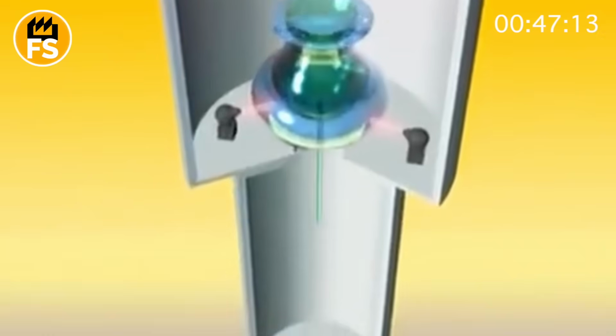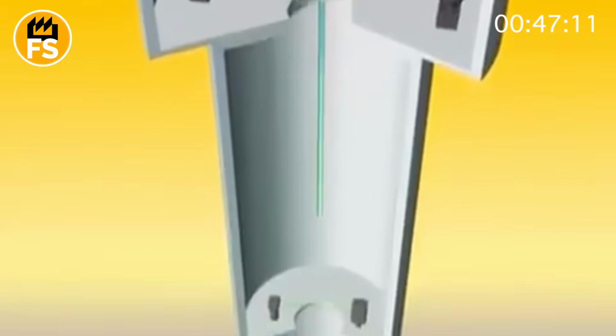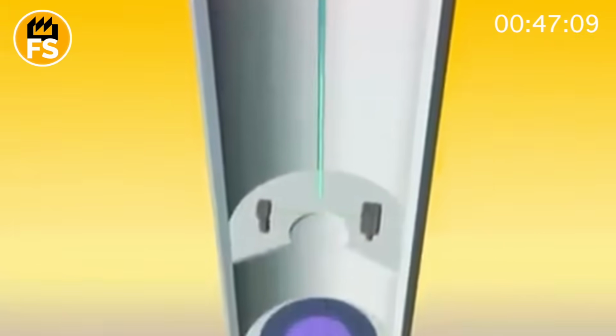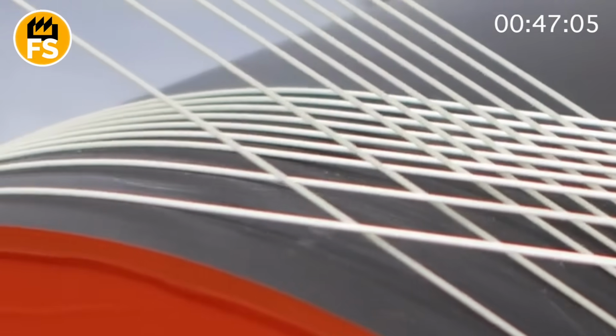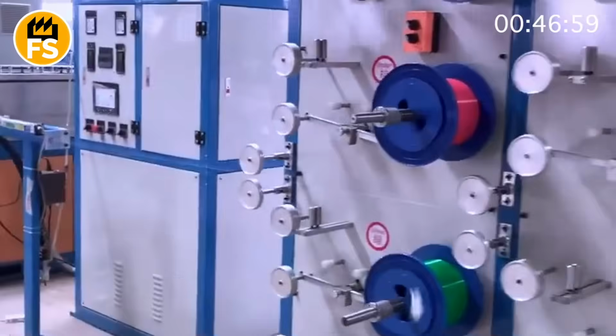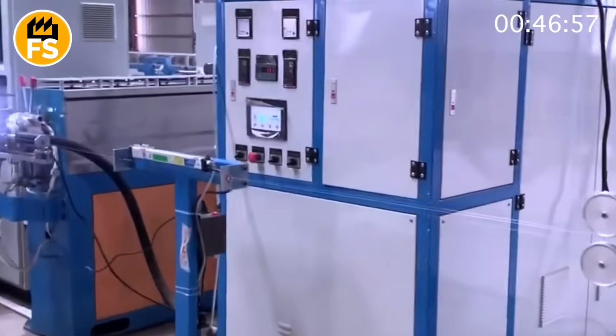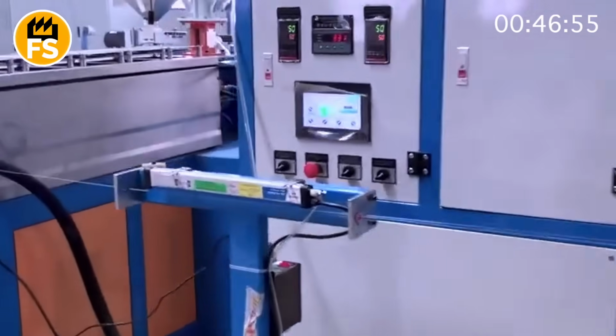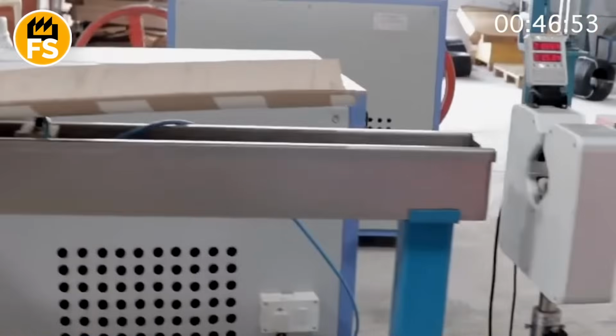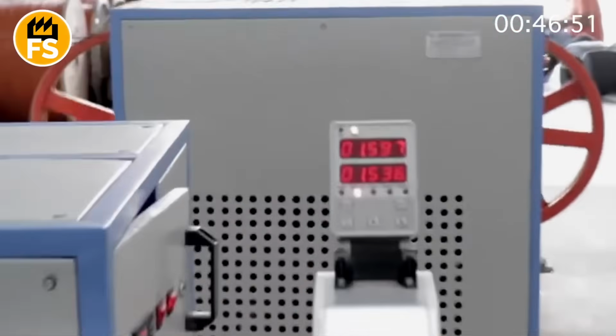This is a very fast process. The coating solidifies in fractions of a second, literally. This method does not heat the fiber, so it doesn't damage it. This provides very strong and durable protection. The entire machine is equipped with sensors and control systems. They constantly measure the coating thickness, fiber feed speed, and uniformity of application. If the coating layer is too thin or there are defects, the system either stops the process or adjusts the parameters to avoid defects.